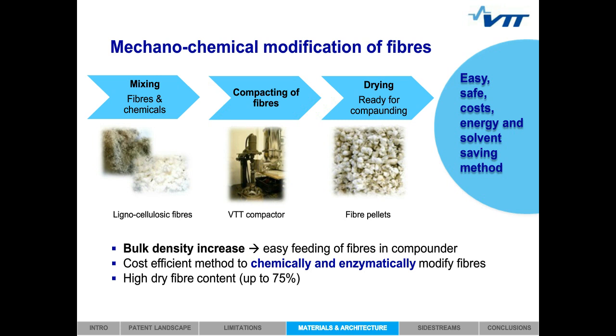It's a so-called mechanochemical process where we are able to compact the fibers so that they are easy to feed into an extruder, as well as we can also chemically modify the fiber. So it's a simple process where the fibers and the chemicals are mixed together, after which they are compacted to compact pellets in a VTT compactor, for which we hold a patent. And after compacting, these pellets can be fed into an extruder. So as a conclusion, the benefits of this process are that first, you get pellets that are very easy to feed into the extrusion process. You can very cost efficiently combine chemicals with the fibers. And also you can work at very high consistency, which further improves the economics of the method.